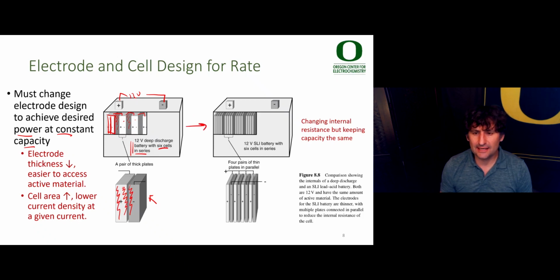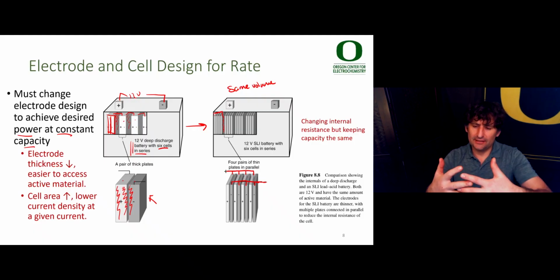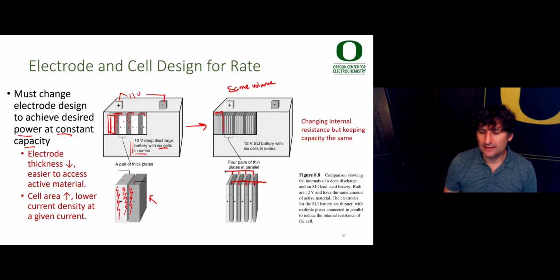Now, I could take the exact same volume of a battery, and instead of making just 2 big plates in each cell compartment, so again, here's the spacers between the cells, here's a cell compartment, I can replace that with sets of plates. So now I have a wire going to 1, 2, 3, 4 negative plates, and 1, 2, 3, 4 positive plates. So essentially what I've done by interleaving the plates in this way and also connecting them in this way is essentially increase the area of interaction between the plates by a factor of 4, because now I have 4 times the area than I did before.